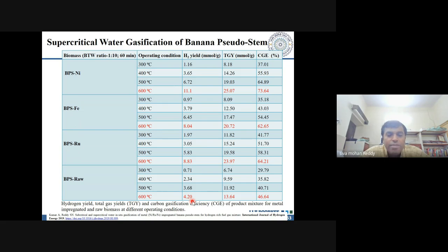You see, we are getting only 4.2 millimole per gram of hydrogen, but for the same biomass, if you have nickel in that, we are going to have almost 11.1 millimole. That means almost 3 times compared to that of your raw biomass. Whereas iron, it is almost at 8.04, that is twice that of your raw biomass. Ruthenium, it is almost at 8.83.